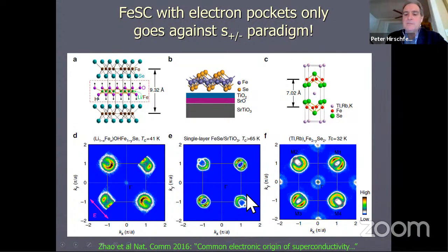So it's suggested that there must be a different kind of pairing taking place here. Perhaps it's just a matter of having scattering between the electron pockets, which are fairly well nested, and that will give you a d-wave order parameter, as it turns out. That's not obvious, but it's true. But the question still remains, why are these materials among the highest critical temperatures of all the iron-based systems? For example, this is 40 Kelvin, this is 65 Kelvin, this is 32 Kelvin. These are quite high, and the one in the middle is actually the highest. So that's really not understood at the present time. There are some ideas floating around.